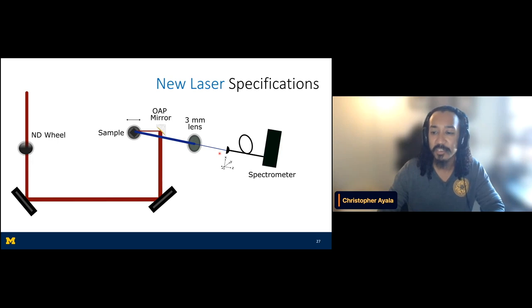And one thing I didn't mention earlier, which this is a good place to do so, is that to generate harmonics, you need about 1 terawatt per centimeter squared focused onto the sample. And with what we have currently, we're sitting right above that minimum limit. So whatever we can do to increase that maximum peak power onto the sample would be a great issue to fix, essentially.